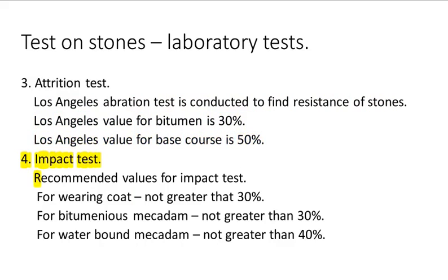4. Impact test. Recommended values for impact test: for wearing coat, not greater than 30%. For bituminous macadam, not greater than 30%. For water-bound macadam, not greater than 40%.